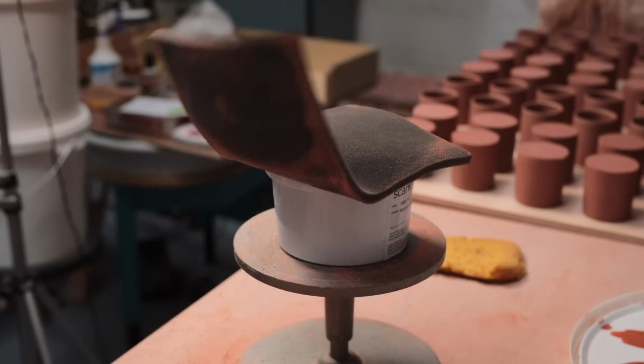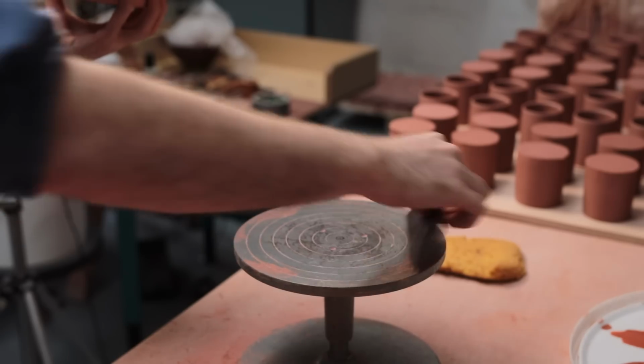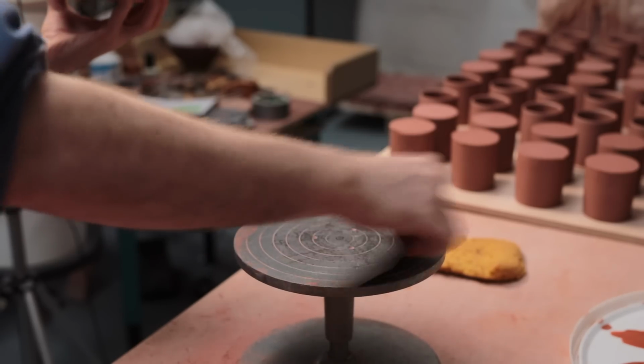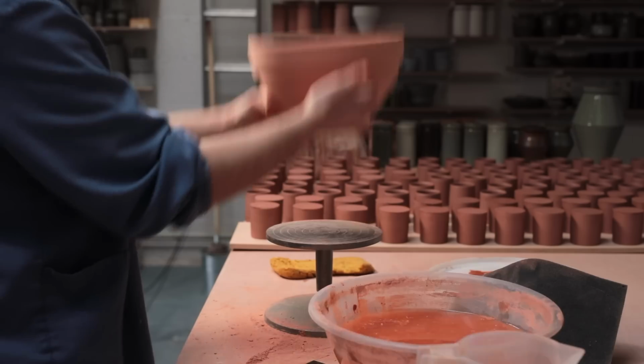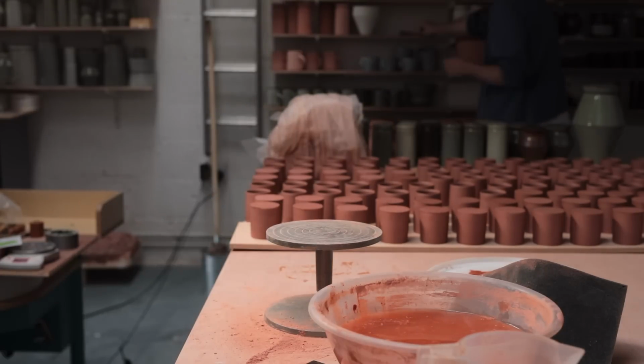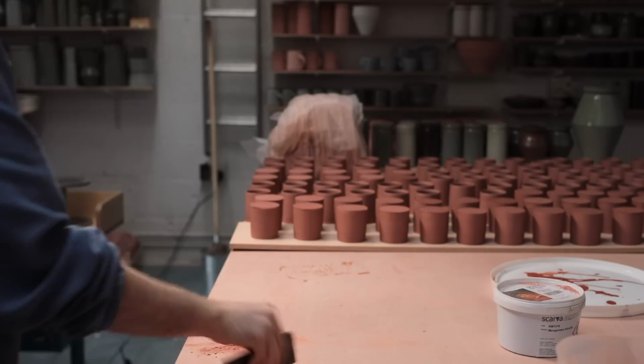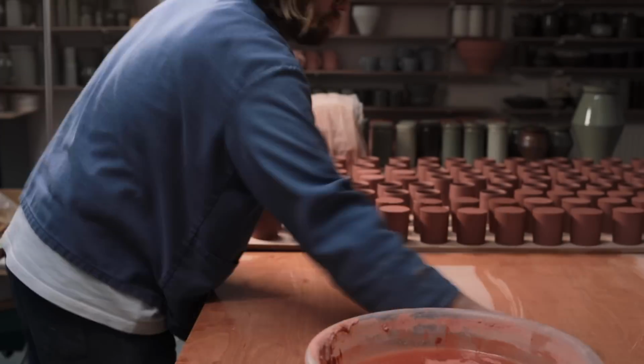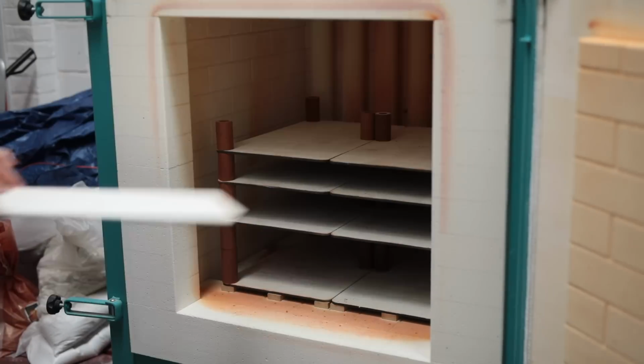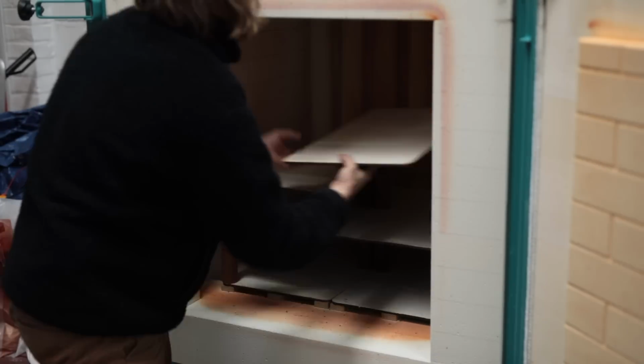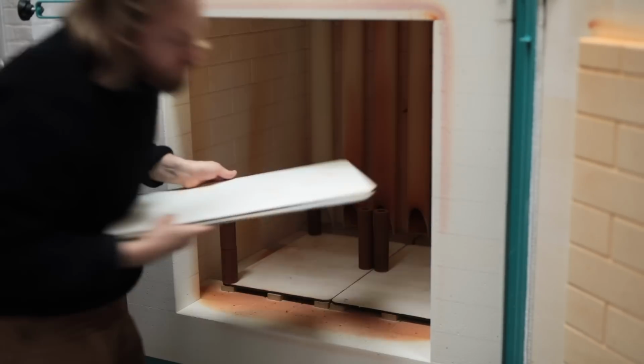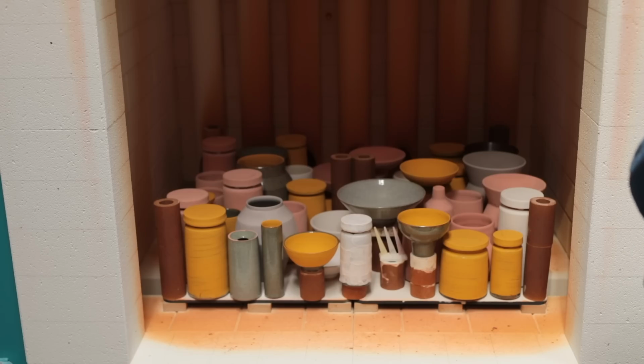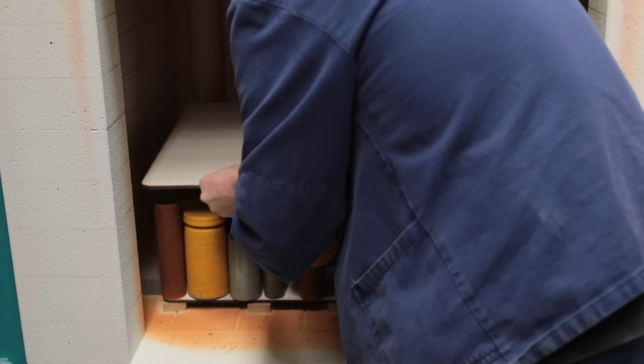And with the two bowls finally finished, I can pack them into my Rohde KG340 gas kiln so they can be reduction fired to 1290 degrees Celsius. This kiln is loaded from the front, compared to my electric kiln which is a top loader. I prefer to pack front-loading kilns like this, although as the shelves go up it can be a little bit more difficult to see what you're doing, as you can't easily see behind the pots you're placing inside, but you learn to pack despite that.